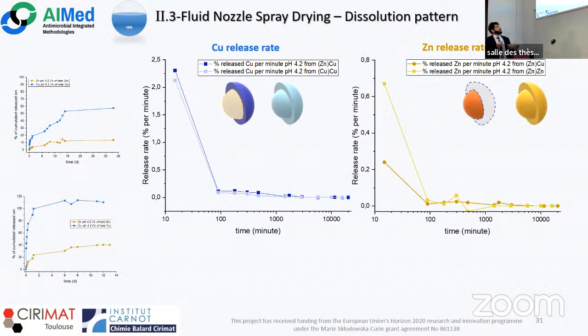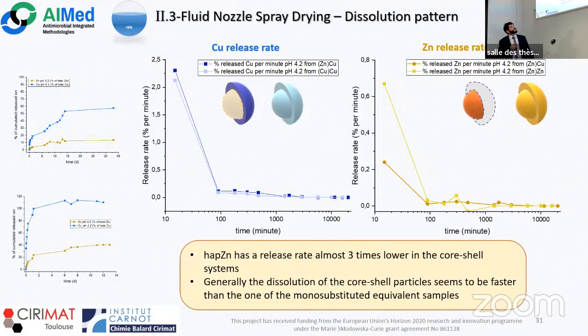And we compared the release rate of the shell and of the core of our core shell particles with the comparable monosubstituted particles. So we observed that the shell of the zinc copper particle had a release rate extremely comparable with the monosubstituted copper apatite particle. But on the other hand, we observed that the core of our core shell apatite had a release rate almost three times lower than the monosubstituted particle. This can be due to the segregation of the zinc within our shell, and also the fact that we don't observe this release starting at a second time. It can be linked to the fact that in this condition, after 10 minutes, almost 10% of the copper is already released. So of course, we expose the zinc in the very first minutes of the process.